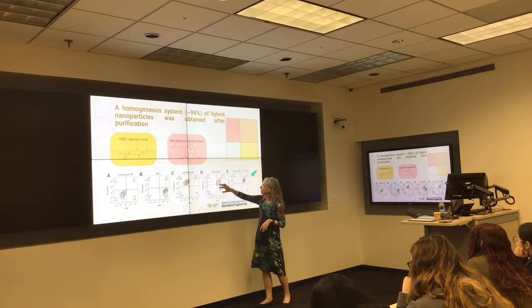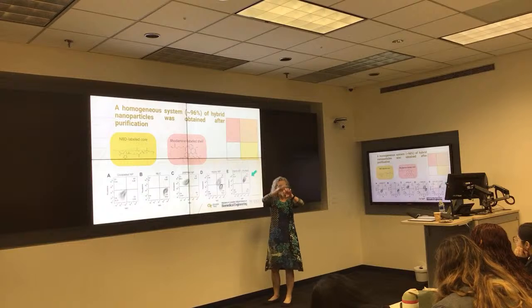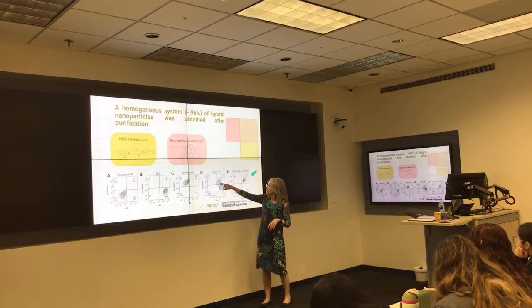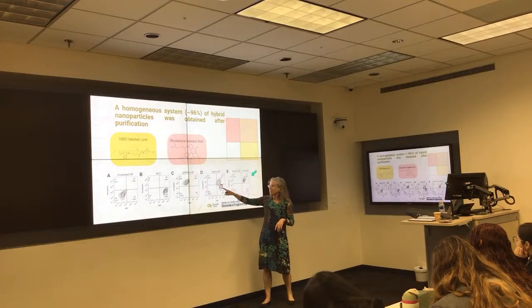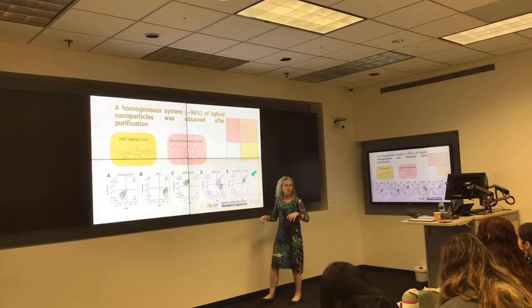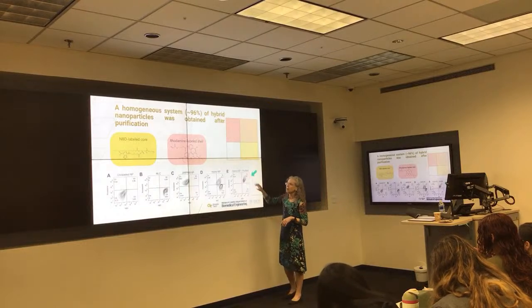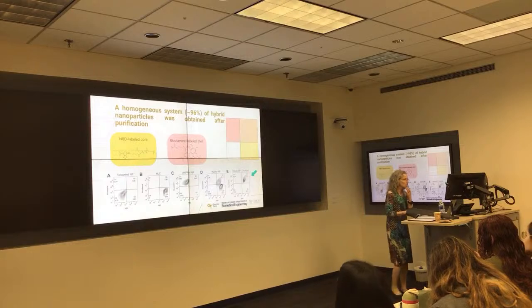And if we have, in theory, something that's the core with the shell has both overlapping, you'll find it in the upper right-hand. So in her particles, when she purified them once, we found there's some just cores, and there's some dual, core, shell around a core. And if we purify them again, we find all shell around the core. So we have a nice purified core shell nanoparticle.